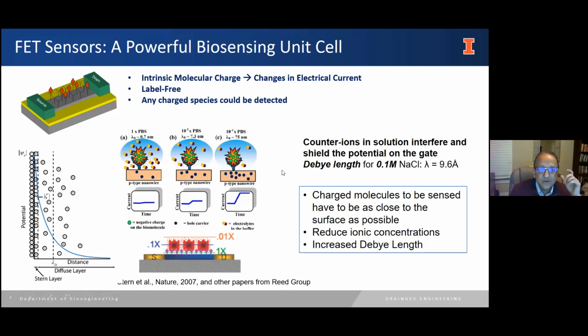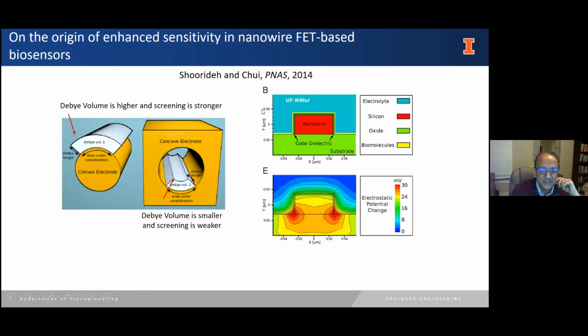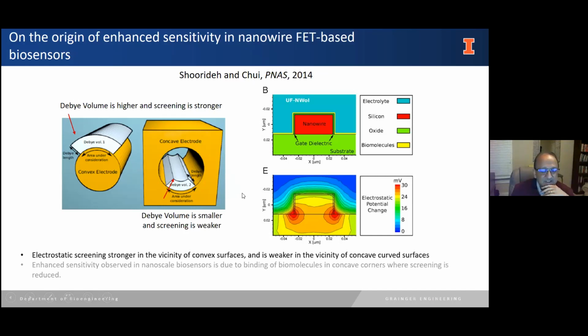So long story short, there was a paper published by Professor Chui at UCLA that was just a computational paper, which projected that if you could make a concave versus a convex sensor, then you might have a difference in the Debye volume and the Debye length. So the screening would be different if you have a curved surface.